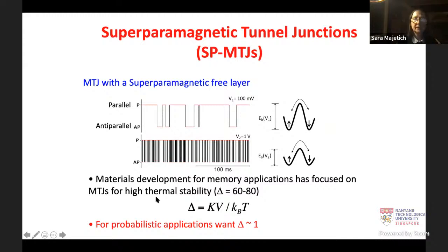In either case, there's a lot of work that's been done to develop tunnel junctions for memory, for MRAM. And usually there, you're thinking about a parameter for the thermal stability, this delta, which is the energy barrier height relative to the thermal energy, that should be on the order of 60 to 80. People who work with magnetic recording media are also using this parameter. But for probabilistic computing, you want a really low barrier because you want the switching to happen quickly. If you're relying on a time average, you want a lot of events within a short time period that you can average and get a statistical average of the property.